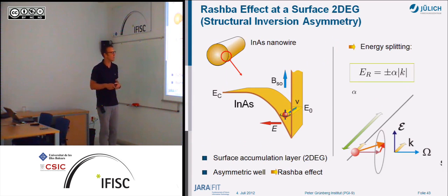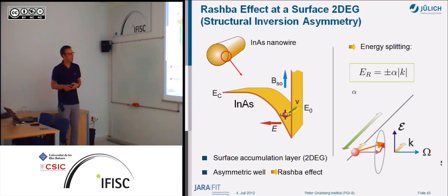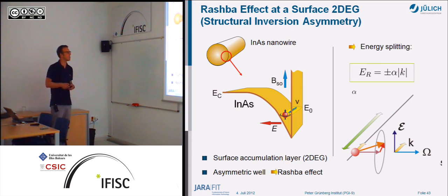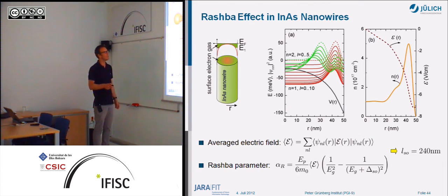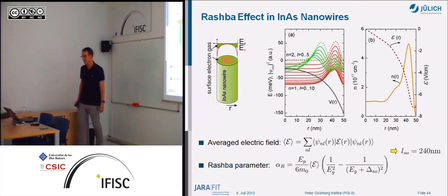the Datta-Das spin transistor. There's no animation here, but while the electron is moving, it produces a particular internal magnetic field, and if the spin is oriented like this initially, then the spin sees that internal magnetic field and precesses around it. This is the precession you have in a Datta-Das spin transistor. The magnetic field is made by this electric field if the electrons are moving in that field. And then you get this spin splitting, which is determined by the Rashba coupling constant.